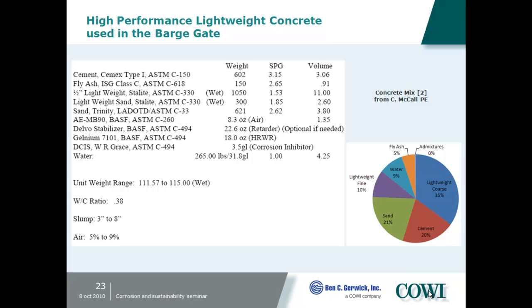And this is more a controversial part, as we did use this DCI. It's a corrosion inhibitor. Normally Gerwick doesn't do that, but to provide a belt and suspenders type of approach, with so many levels of review and all questioning it and refusing to allow you to do anything in the future, it was an approach that managed to satisfy all the different reviews. So of course here you can see that we had lightweight coarse, natural sand, some lightweight fines, and 20% cement here in this case, because heat of hydration is not an issue.